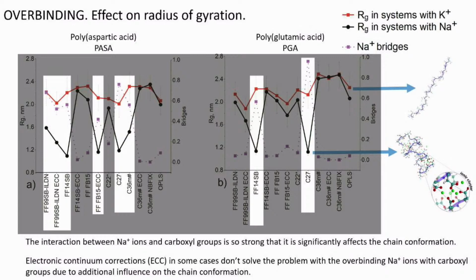What's the reason for such behavior? It is overbinding, as I said before. This overbinding leads to formation of sodium bridges between charged carboxyl groups. You can see by the pink line that the amount of such bridges is very high in the cases where the difference of radius of gyration between 2 different systems is high.